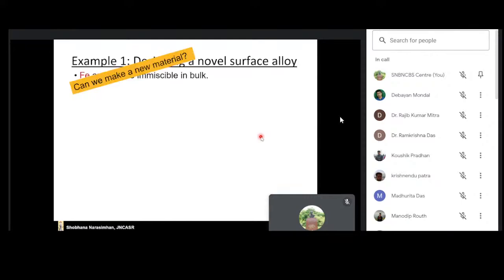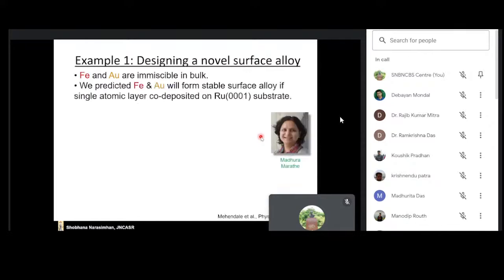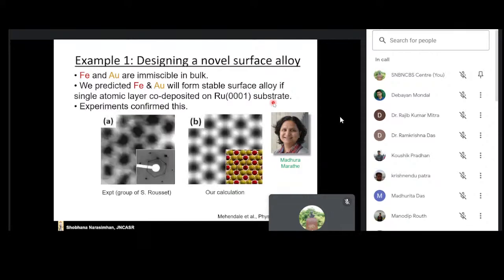So I come now to the first one: can we make a new material? Alloys are made by mixing together 2 or more metals, but not all metals can be mixed to make an alloy. For example, iron and gold are immiscible in the bulk. You can't really make an alloy out of iron and gold. But we predicted that if you take a single layer, just one atomic layer thin, of iron and gold, they will form a stable surface alloy, as it's called, if they are co-deposited on a ruthenium substrate. Okay?